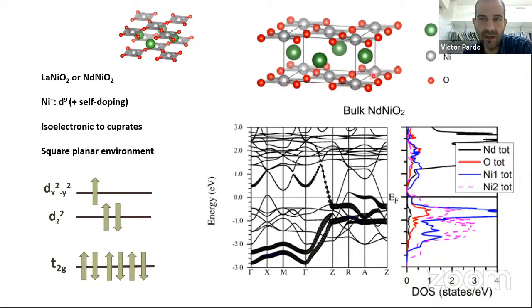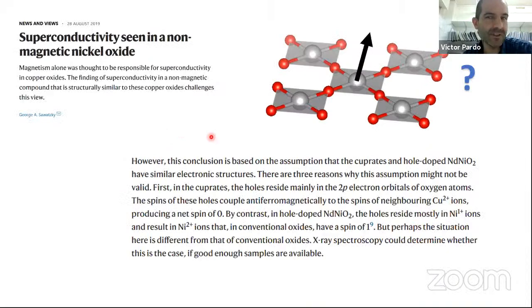But yeah, the structural situation, these nickel-O2 planes are just like in the cuprates. So one of the questions that we tried to address first was, okay, we have this neodymium nickel O2, we want to dope it with strontium, and if you dope neodymium nickel O2 with strontium, you move from nickel 1+ to nickel 2+. And like George Sawatzky pointed out really early, in conventional oxides, nickel 2+ is spin 1. So what is happening here? Are we doping with a spin 1, and does this make it different than the cuprates?